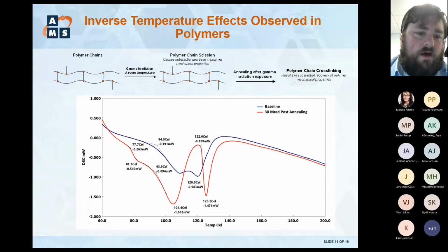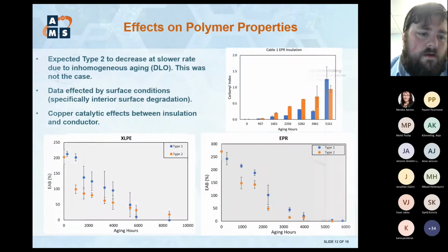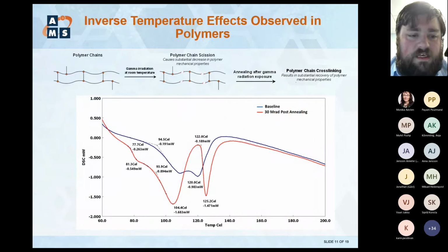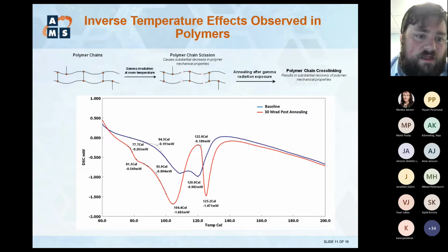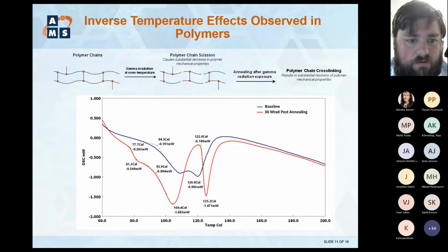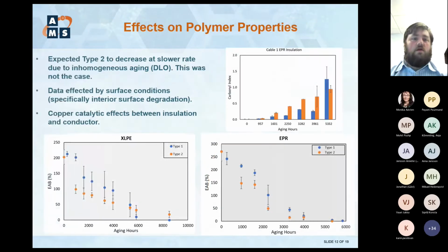I'll go quicker. So all I show in this plot is just the DTA or DSC scans I've got for the material. The polymer chain cross-linking process does happen because you get these lower temperature mobility crystalline regions that actually allow the chain, when you heat it up at the aging temperatures, to go through the cross-linking process. So now I want to get into the effects of some of these things on the polymer properties we've seen.